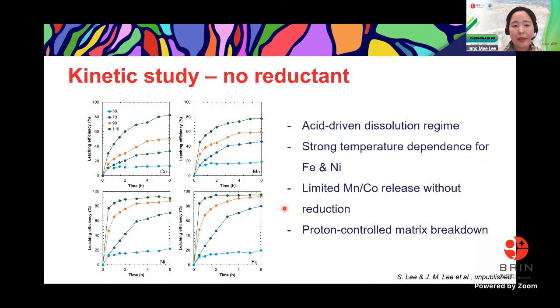So yeah, and then we've done the kinetic study at the different temperature. The previous leaching test just made a difference in terms of the addition temperature, but all the leaching tests for 6 hours were done at 110 Celsius. That was the criteria, that was the requirement. The reason why we fixed the leaching temperature at 110 Celsius is, I told you this is the industry collaboration, and 110 Celsius is sort of the optimized condition that our industry is considering to apply to the pilot plant.